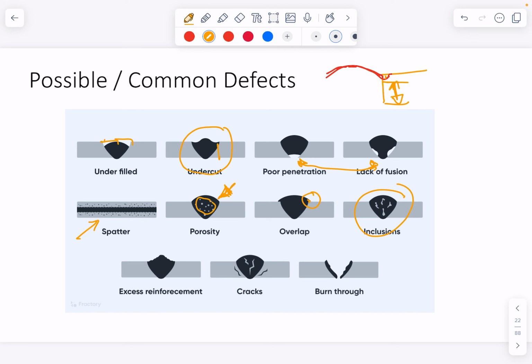Excess reinforcements, self-explanatory. Cracks. So if I use the wrong filler material or I use the process wrong, I might get cracks here in the heat affected zone, or I might get cracks in the weld pool itself. And so that's obviously going to cause early breakage under loads. And so again, understanding the process and what it is you're welding and what you're trying to achieve is sort of the first step in understanding this sort of stuff.